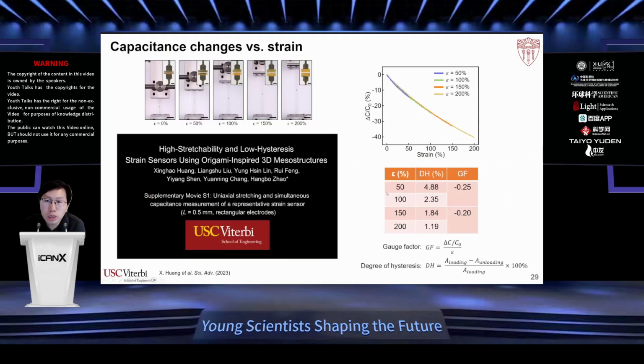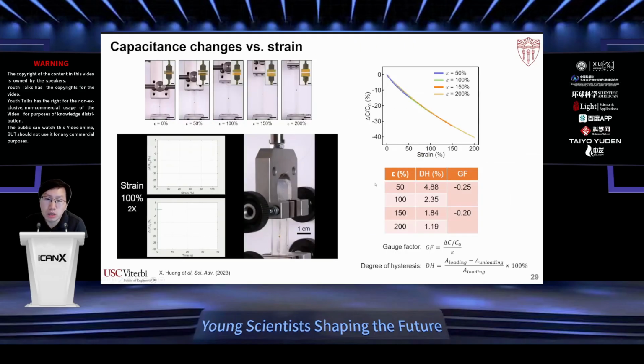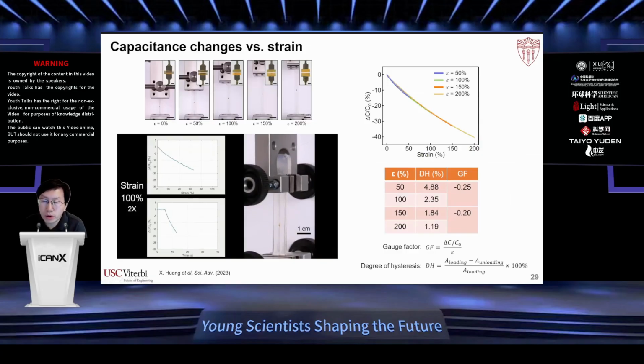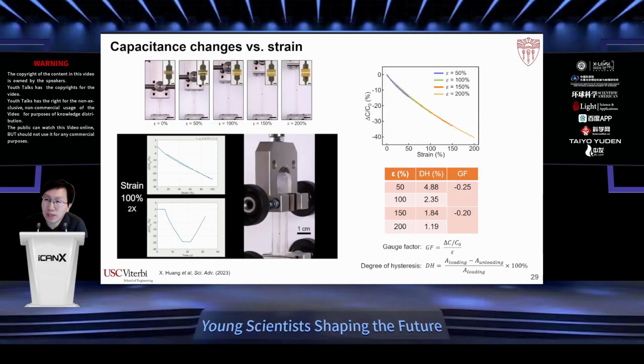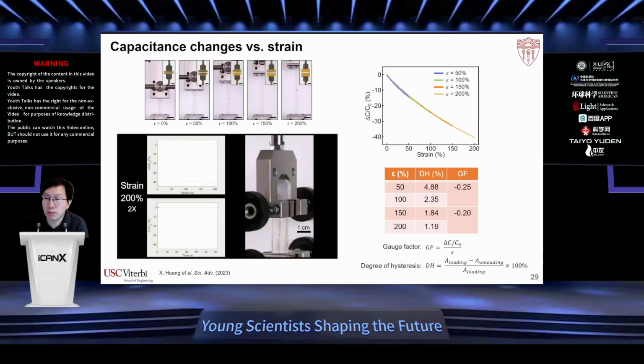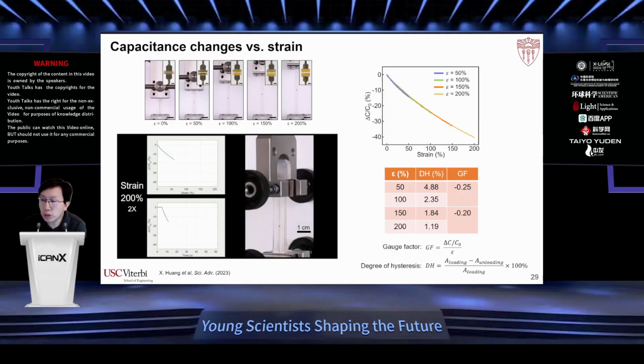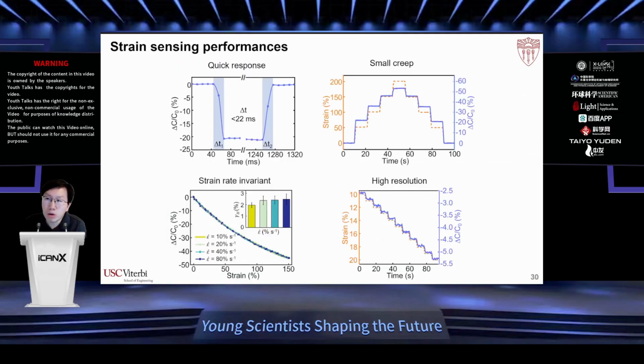So you can see here, because this deformation is entirely driven by the folding and unfolding of this triangle, we can achieve pretty large strain range as long as we choose a large pre-strain. And because the capacitive change is driven entirely by the substrate deformation, there's no material change, so we can achieve low hysteresis. And we can also have quick response, strain rate invariant, high resolution strain sensor result.